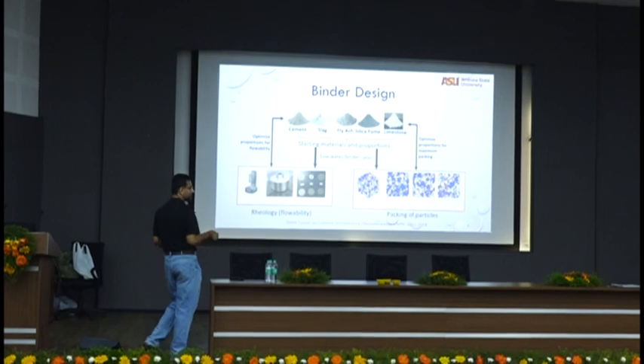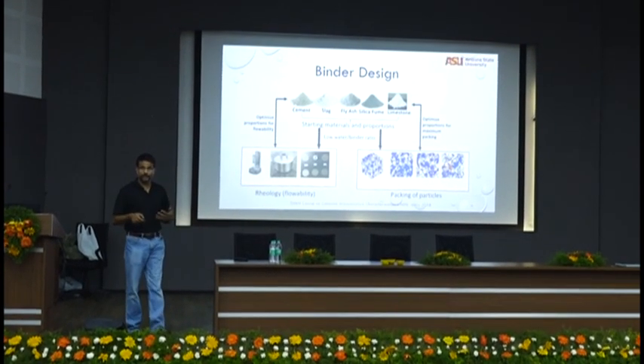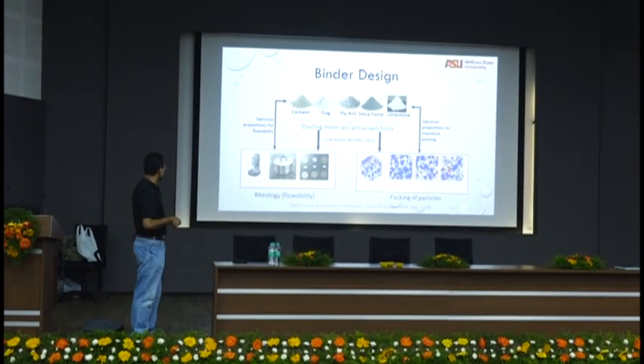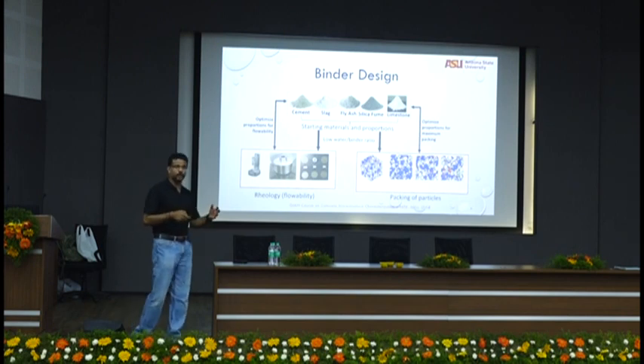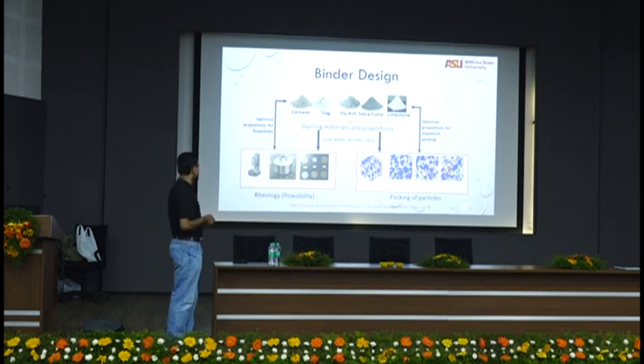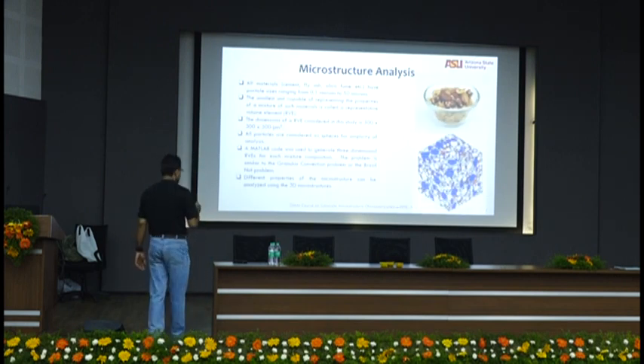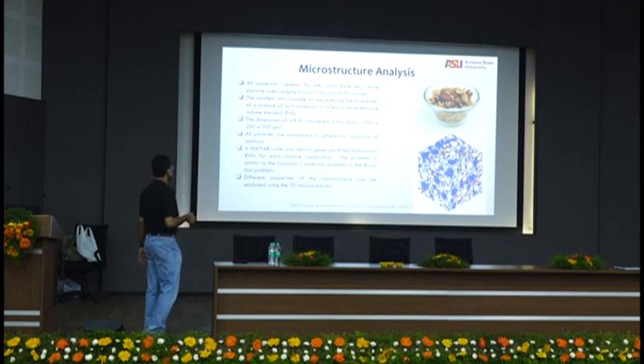And then, because this mixture needed to be really fluid and flowable, we wanted to check for rheology also, along with that, because your water cement ratio is 0.18 and you really needed very good workability. So all mixes have particle sizes ranging from 0.1 microns to 50 microns.